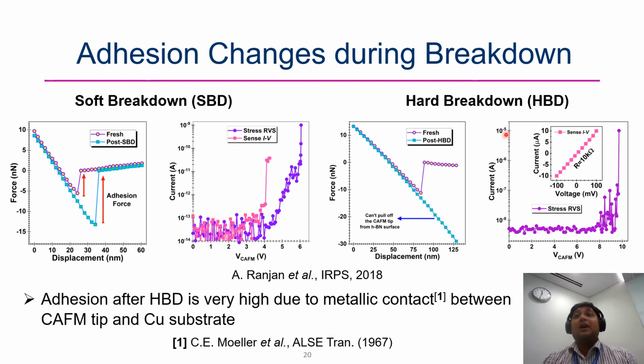However, in the case of hard breakdown, we can see that the post-breakdown resistance is around 10 kilo-ohms, which is very close to the series protection resistance that we have put. So it shows that in the hard breakdown case, we have formed a metallic contact. In our case, it was a platinum wire tip. So most likely under hard breakdown condition, it has removed the copper, it has removed hBN, and now the platinum wire is in direct contact with the copper. And therefore the adhesion is huge, because two metals in ultra high vacuum conditions are known to form very highly adhesive contacts.